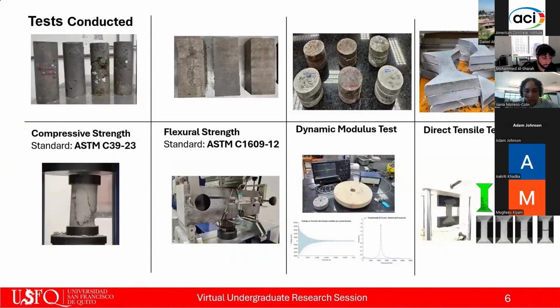Compression tests were performed on 4 by 8-inch cylinders after 28 days of curing. Flexural strength of the fiber reinforced prisms was measured following ASTM C1609, also at 28 days. A key parameter of this study was the dynamic modulus of elasticity, assessed on 4-inch discs, 1-inch thick, made with different aggregate and fiber combinations.